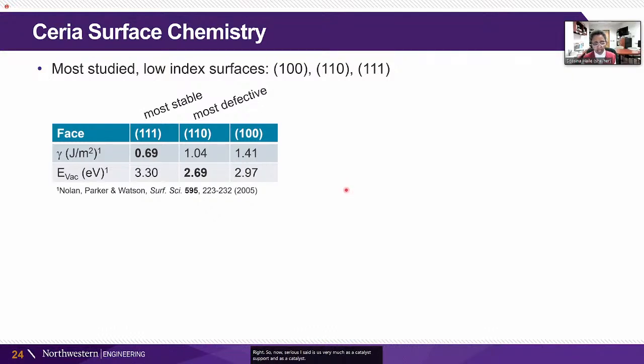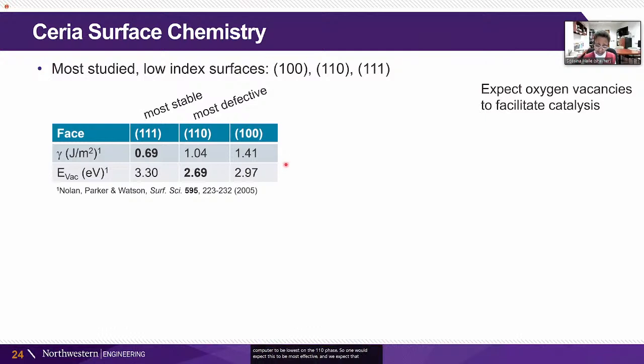Right. So now ceria, as I said, is used very much as a catalyst support and as a catalyst itself. And there's a lot of interest in the surface chemistry. The different terminations here have been studied in terms of predicting both the surface energy as well as the vacancy formation energy. So the surface energy is lowest for the 111 phase, so you'd expect that to be most stable. The vacancy formation energy is computed to be lowest on the 110 phase, so one would expect this to be most effective. And we expect that oxygen vacancies on the surface would somehow facilitate catalysis.